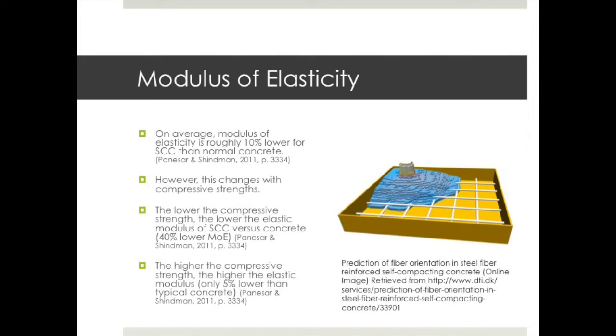Due to the lower aggregate content in SCC than in typical concrete, it has been found that the modulus of elasticity is approximately 10% lower in SCC than in standard concrete with the same strength. This has been found through multiple tests and literature on the topic of elastic modulus in SCC.